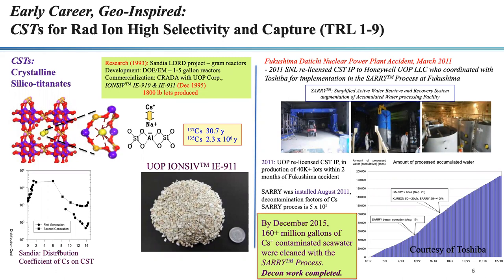Using geology as a basis, we developed crystalline silico-titanates — a silicon and titanium framework connected by oxygens — where at the atomic scale we form the perfect pocket for a cesium ion. In our second improved generation, we have a material with orders of magnitude higher selectivity for cesium over sodium. Remarkably, from 1993 to 1995, we had the discovery, fundamental understanding studies, and scale-up to commercialization. This is now a commercial product sold by Honeywell UOP as an ion sieve.